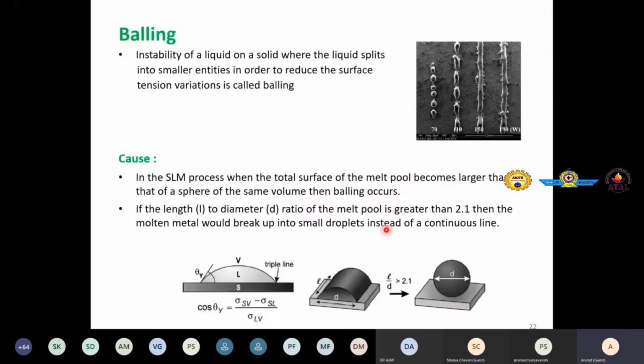So balling defect is something you can see in the photograph on the right hand side. Instead of a continuous track, we obtain a spherical ball kind of track, right? And this is because of inappropriate choice of process parameters. So what happens? Balling is something like instability of a liquid on a solid where the liquid splits into smaller entities in order to reduce the surface tension variation. So it is caused when the total surface of the melt pool becomes larger than that of a sphere of the same volume, then balling occurs.